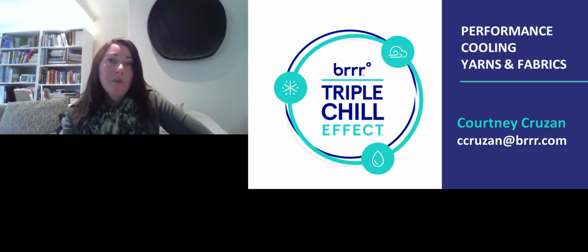Another example would be adding a sublimation print to a performance fiber polyester: you run it through a sublimation machine that presses and prints, through a heat press application. We also run the fabric through calendering or ciré, which flattens it or adds a shiny effect to the fabric, and that doesn't affect the performance of the fibers.